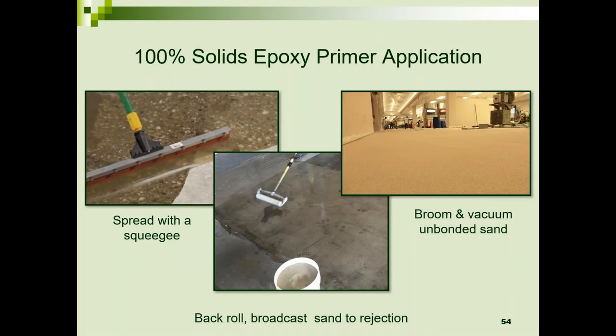And typically with epoxy and sand installation, you're spreading out the epoxy, you broadcast sand to rejection, remove the excess sand, and you're ready to go as far as tile installation or underlayment installation, once that floor has been cleaned of any residual sand or loose material.